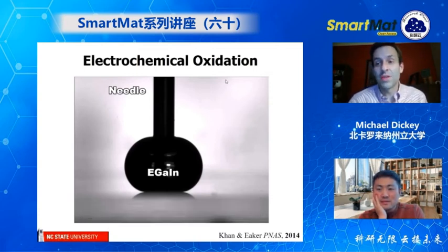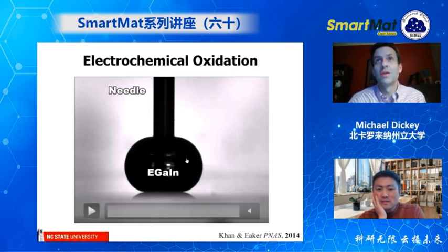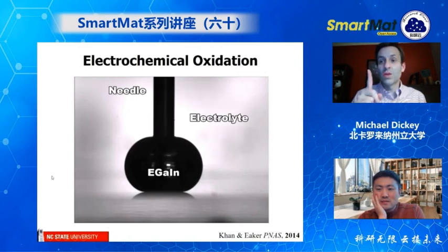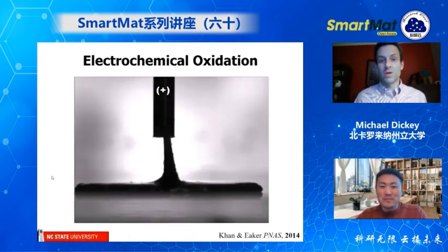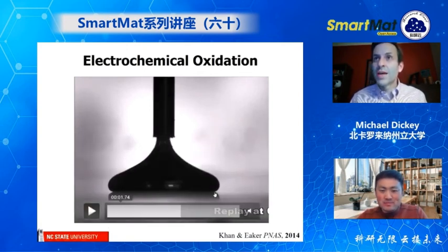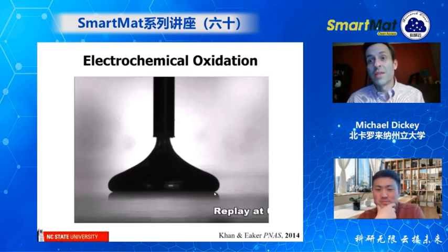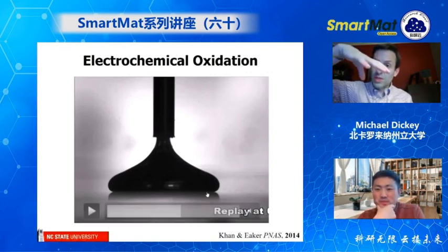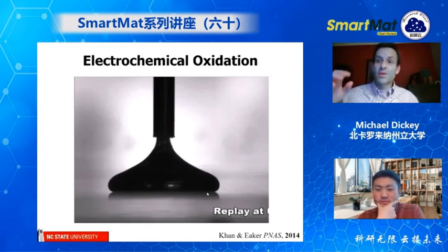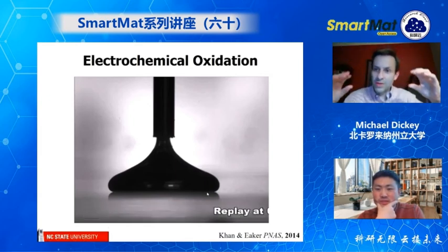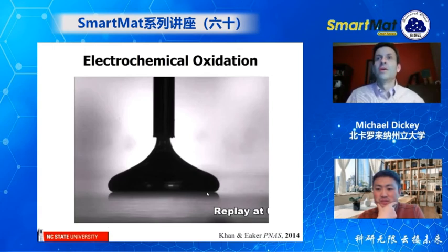It's not an effect of electric field forces. It's simply because we're depositing species on the surface electrochemically. So when we do this, again, 1 volt, not 300 volts. It's much, much smaller. And secondly, if you watch, when it starts spreading, the contact angle doesn't change very much. With electrowetting, you actually change the effective contact angle. Here, all we're doing is lowering the tension, and gravity is just causing it to sag down.